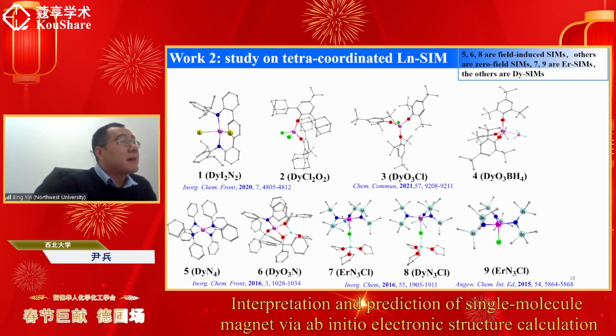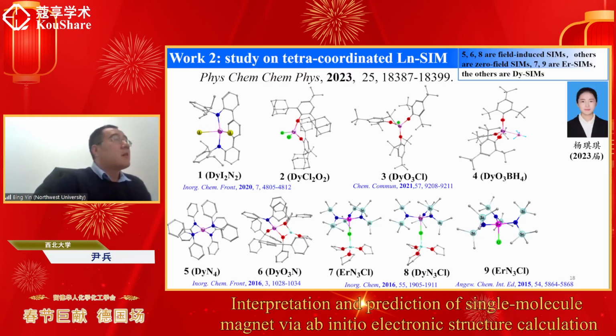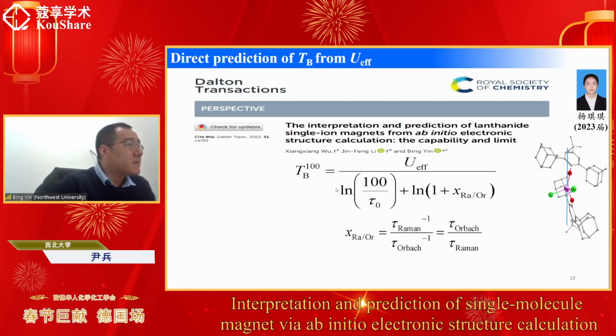And the second one is the study of some tetracoordinated single ion magnets. This work was published last year. We collected some four coordinated systems, and then we did ab initio electronic structure calculations of these systems to predict their QTM time as well as energy barrier, and to interpret the experimental findings. In this work, we also make some prediction of the blocking temperature, because in this paper we also propose an equation to calculate blocking temperature based on the calculated energy barrier. In this equation, we use the energy barrier calculated by the ab initio result, and also the tau zero as well as this X parameter, which can be empirically estimated based on the available experimental data.